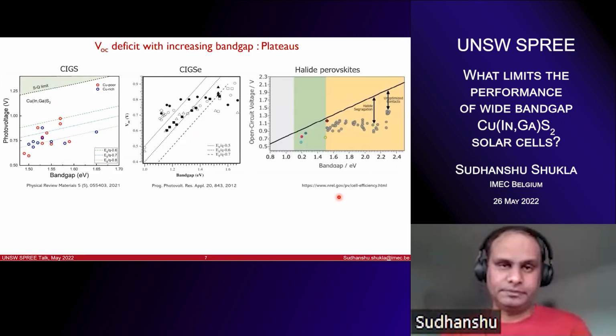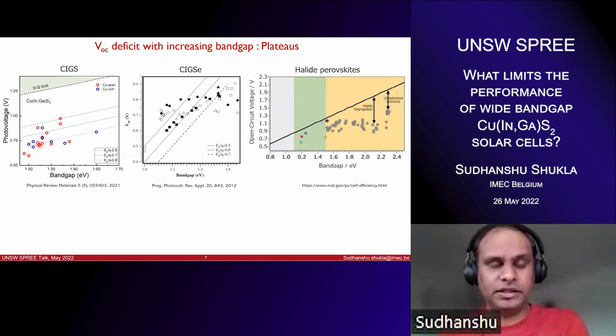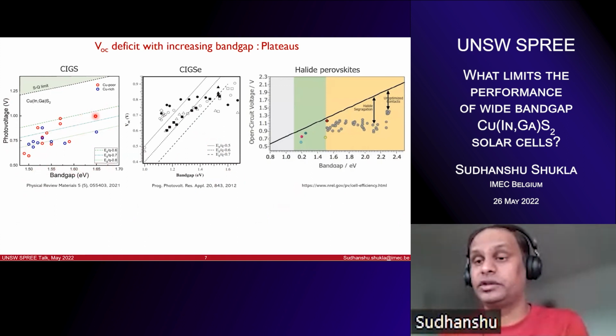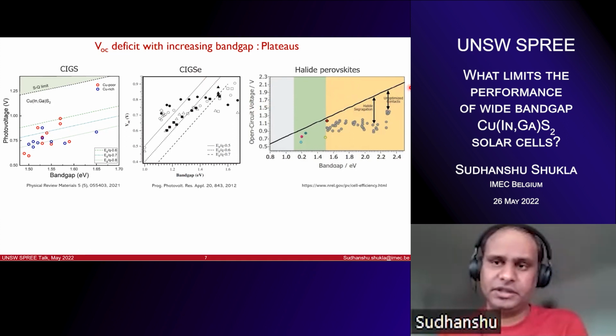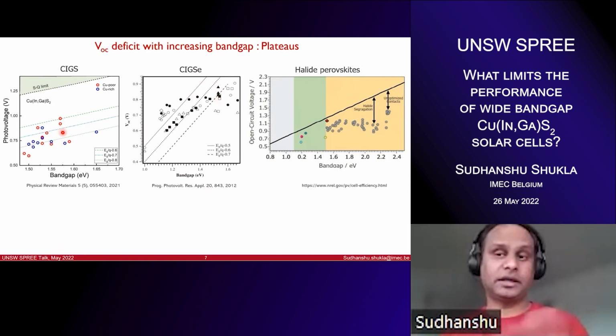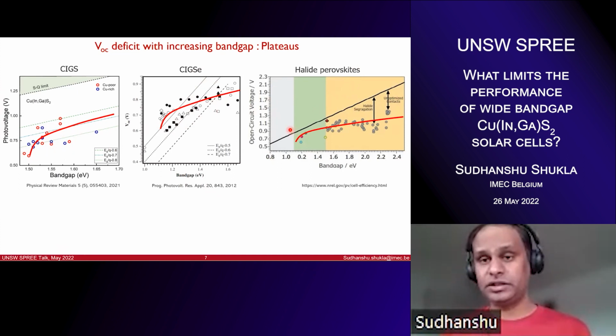So these are the three different technologies or semiconductors that you are looking at. The VOC deficit: if you increase the band gap, your VOC deficit increases. This is what it tells you, that it doesn't scale, which means if you increase the band gap, the VOC does not increase linearly, but rather limits itself. The same happens with selenide, the same happens with halide perovskites as well. Although their origins are different: for perovskites, it's halide segregation and unoptimized contacts; for selenides, it's the gallium, as I just mentioned, the deep defects; for sulfides, we know the least among all three. So you see the plateauing behaves in a similar way in all these technologies, although the plateau is shifted up or down. It's more or less true that when you increase the band gap, the VOC generally does not scale with the band gap. It limits itself.